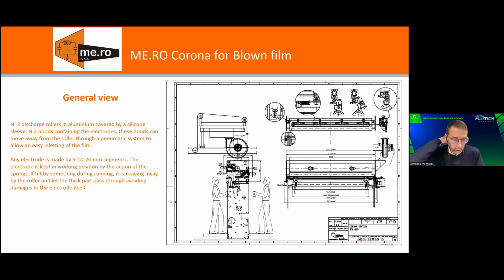So you do not lose the gap with our system, and this is possible because we have a special design. Don't forget that we're coming from the big lines, the 10-meter lines, and we bring the same philosophy also on the small lines like treaters for blown film lines. The philosophy is to have a special design with the possibility to expand freely for all the mechanical parts inside, on the electrode and on the support of the electrode. In this way, when the temperature increases, the gap remains perfectly uniform. So this is another very, very important characteristic.